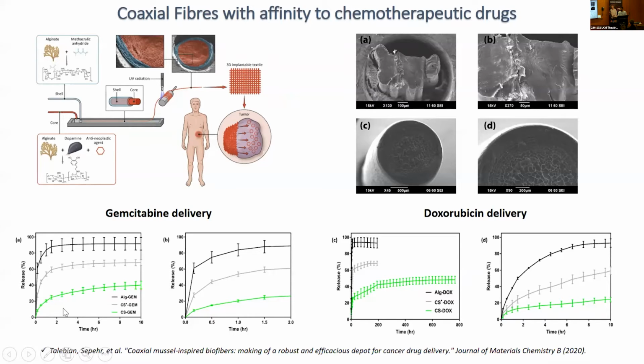But then what we observed was that the core shell fibers that we designed gave us the slowest release rate out of all these other formulations. And then when we looked at doxorubicin, we actually got a better result, because doxorubicin is generally a larger molecule with more functional groups on it. And with the core shell fibers, we were able to get a week of release from these fibers when we tested them in vitro.